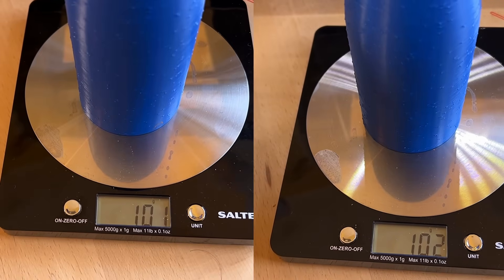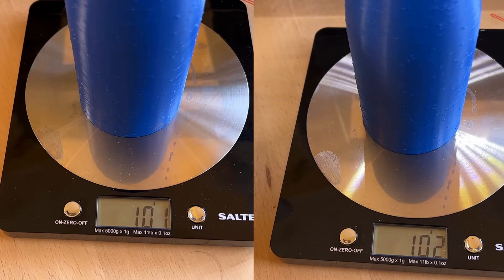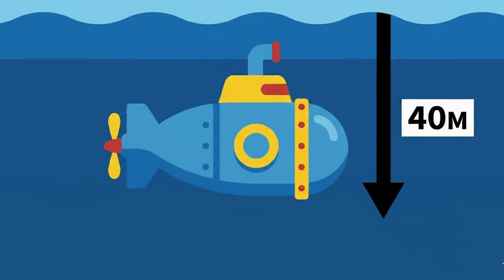Again, no change in mass. So again, they're both completely waterproof at 4 bar of pressure, equivalent to 40 meters of water depth. That is fantastic.